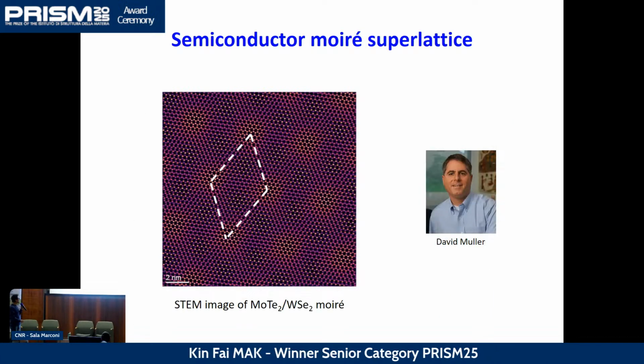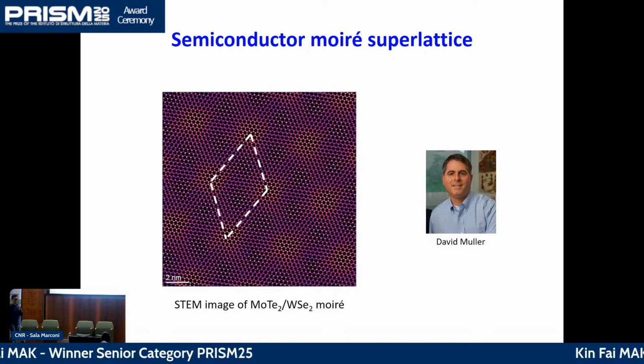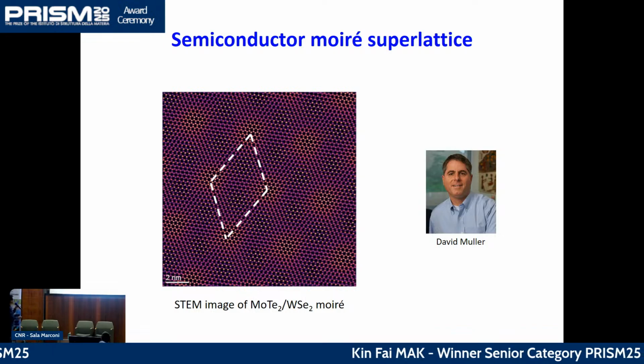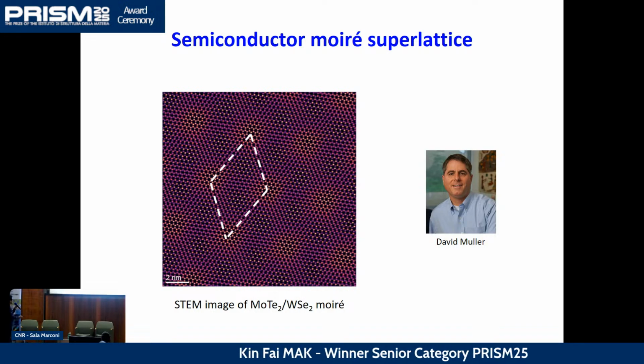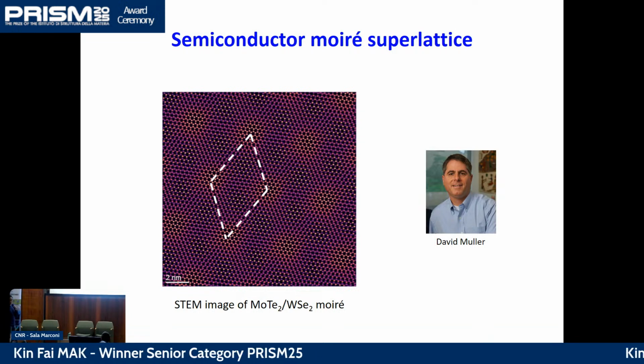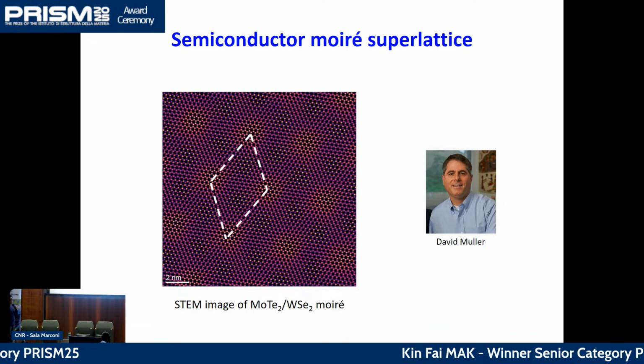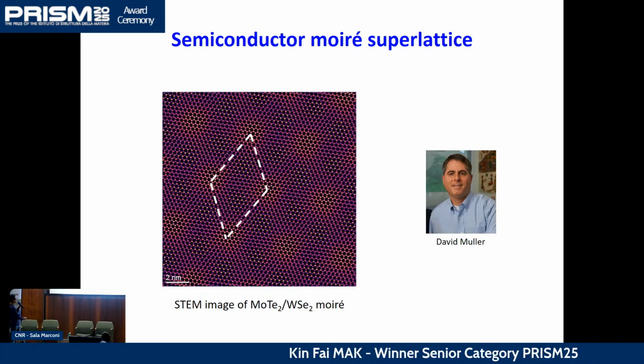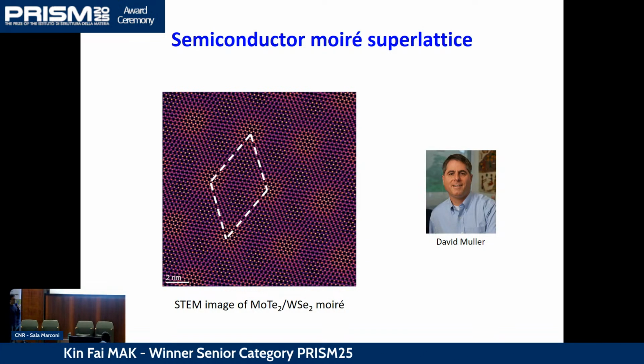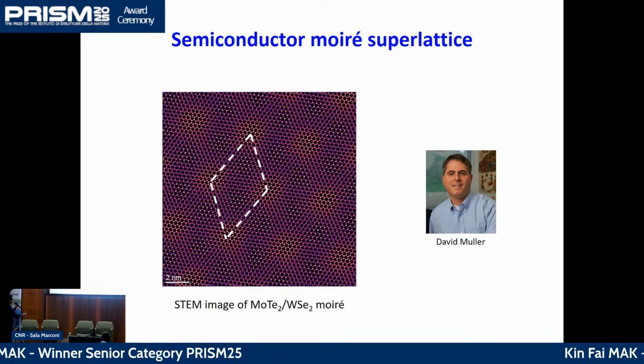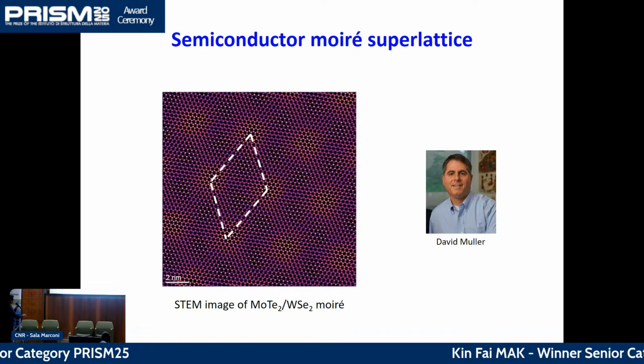Okay. And these moire lattices are real. You can directly see them in the electron microscope. For instance, this is work with Dave Muller's group at Cornell. This is a STEM image of this particular moire material, molybdenum ditelluride aligned with tungsten diselenide. The small dots here are the real atoms. They are angstrom level. But on top of that, you can see the emergence of a superlattice structure, with the unit cell enclosed by these white dashed lines here.